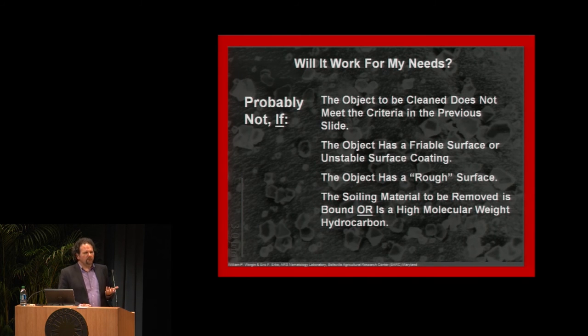Moving on, you notice this slide has a red border around it. If you're not meeting the parameters of the previous slide and you've got things like friable surfaces, that could be a problem. Although if you're trying to remove that friable surface, you may have an advantage, because the solid CO2 has the potential to get under a coating, break it up. Again, I had spoke briefly about depressing the glass transition temperature. You may actually get some really good effect from that. Rough surface, rough is a relative term. If you're talking about a micron-sized snow particle and you're trying to use it on a surface that has millimeter size mountains and valleys, you're probably too rough a surface. If, however, you're talking about a 3-millimeter pellet, maybe not so much.